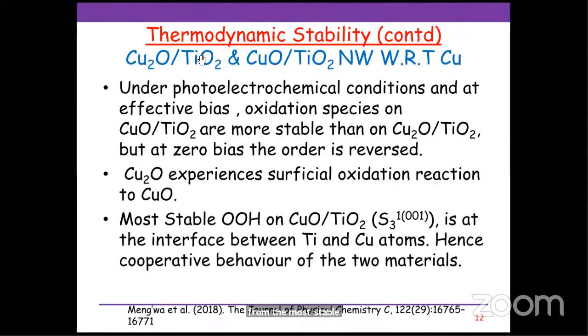Then under photoelectrochemical conditions and at effective bias, we have seen that oxidation species on CuO over TiO2 are more stable than on Cu2O over TiO2. But at zero bias, as I've mentioned, the reverse is the case. Now, what we know is that Cu2O experiences superficial oxidation reaction to CuO, and again, the most stable species is OOH, which is actually at the interface between Ti and the copper atoms. Hence, we have a cooperative behavior of the two materials. Now, we already know this reaction again is...